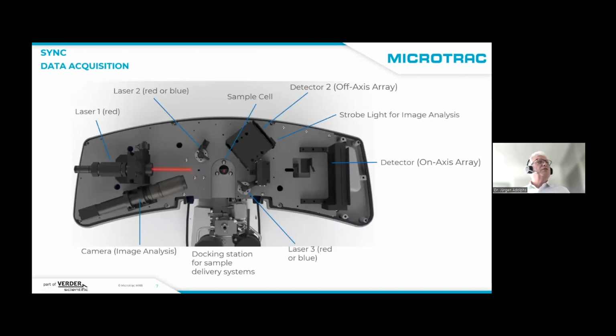The view inside of such a device, you see here the up to 3 lasers, laser 1, 2, and third laser, and an array of detectors. Detector 1, which is on axis between the laser 1, for example, and the detector 2 for off axis. We have here the sample cell. So these are the docking stations we can choose. I will not show the video right now, but what is important, we do have here a camera. So we can measure the particle size by the laser diffraction technique, but we can also see particles.